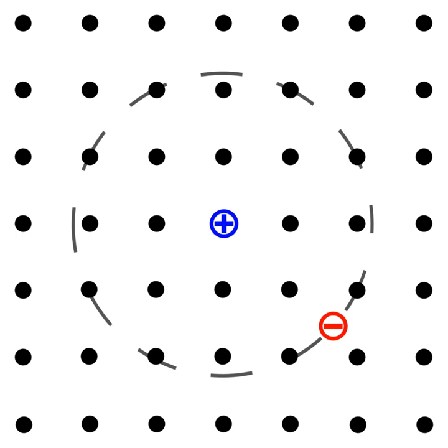Topic: Giant oscillator strength of bound excitons. Excitons are lowest excited states of the electronic subsystem of pure crystals. Impurities can bind excitons, and when the bound state is shallow, the oscillator strength for producing bound excitons is so high that impurity absorption can compete with intrinsic exciton absorption even at rather low impurity concentrations. This phenomenon is generic and applicable both to the large radius Wannier-Mott excitons and molecular Frenkel excitons. Hence, excitons bound to impurities and defects possess giant oscillator strength.